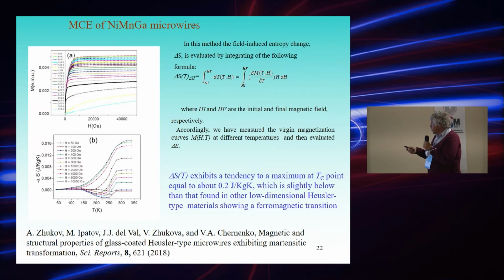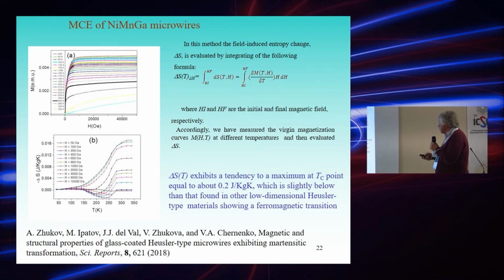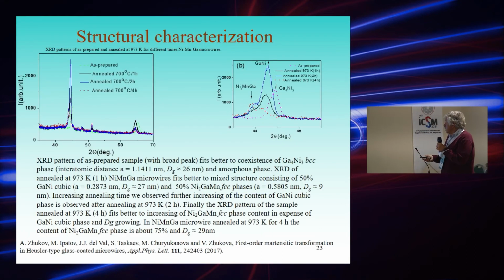So we tried to evaluate the magnetocaloric effect using a conventional method. The magnetocaloric effect was not big, but still we observed some magnetocaloric effect in this material. And we also performed some structural studies.